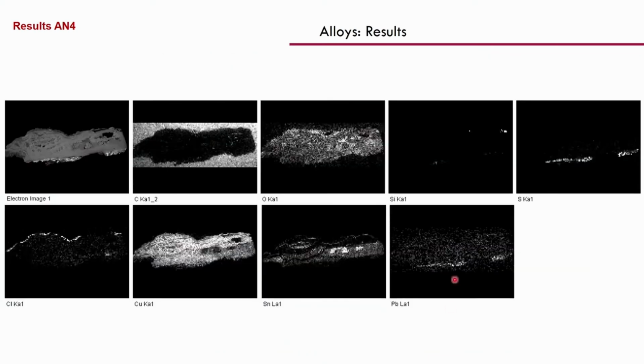And in this case, it was interesting to see, of course, the alloy and the mineralized phases of the tin alloy, so the bronze. But you see that we found the lead concentrated in the external part of the cross section, and it is in some way associated to the presence of sulfur. So maybe this could be solder used for the tibia, and that could be a hypothesis.